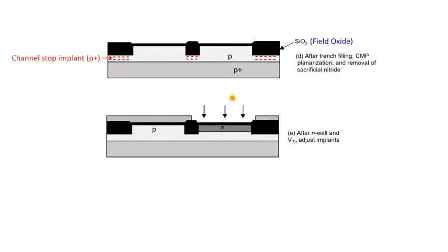So how can we create this N region here? We need to do an implantation of group 5 material or donors, so that this region now becomes N type, okay, and this N region is called the N well, right. And while doing so, we have to remember that this implantation should happen only in this region. So during this implantation, the other region should be protected, okay. So you can see here we have protected this region, we have also protected this region by using some buffer layer.